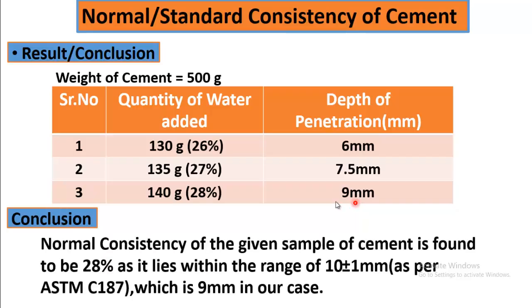So the conclusion is that the normal consistency of the given sample of cement is found to be 28%, as it lies within the range of 10 plus minus 1 millimeter as per ASTM C187, which is 9 millimeters in our case. I hope you have understood the procedure.